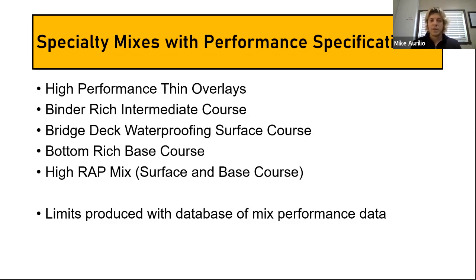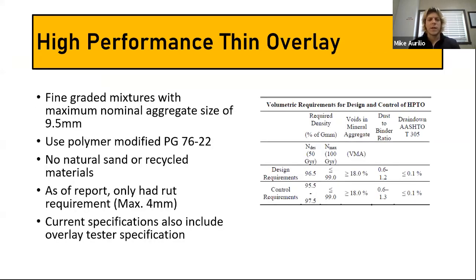And I'm going to talk about 3 of those mixes just to give you some examples and talk about a little bit about how some of the lessons from these mixes can be applied here. So the high performance thin overlay, and at the end I'll wrap it up, but you'll start to notice there's a little bit of a trend in some of these. The high performance thin overlay is a fine graded mix. It's got a 9.5 millimeter nominal maximum aggregate size. I'm not a mix guy, so I got it backwards. They use polymer modified asphalt. They don't use any recycled material.